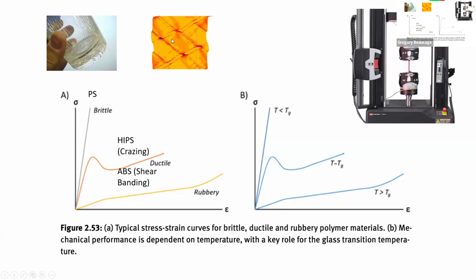The shear banding is a lot easier to understand. You make the material softer and it shear bands, like it's more ductile. If it's brittle, it won't do that. So the curve will look exactly the same though. You get a peak, it'll start to shear band, and then all along while you're pulling it out, shear banding, it hasn't failed, and finally it reaches too many shear bands, they lock with each other and it fails. That's like deforming a metal and getting slip planes in it. Kind of the same thing happens. And then if you get it too soft, it'll just be a rubber and it just deforms like that. It doesn't have a yield point and it stretches out. So those are the three kinds of mechanical behavior of plastics. And they're basically tuned in polystyrene.